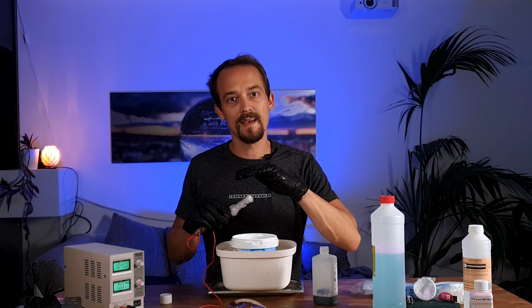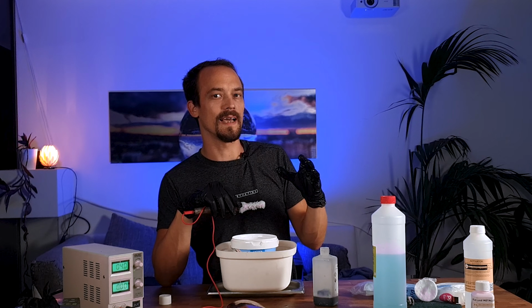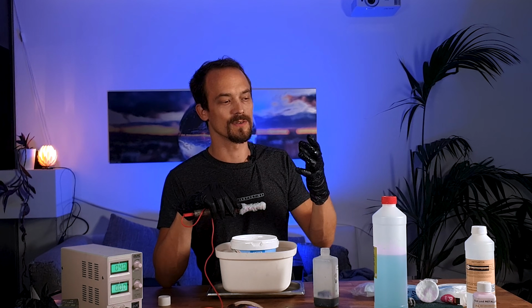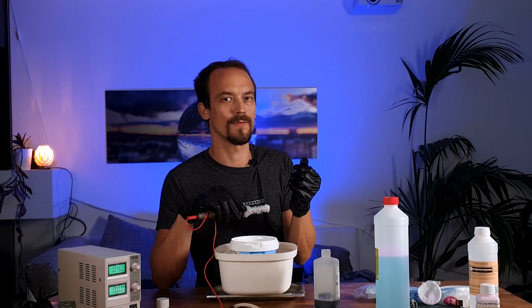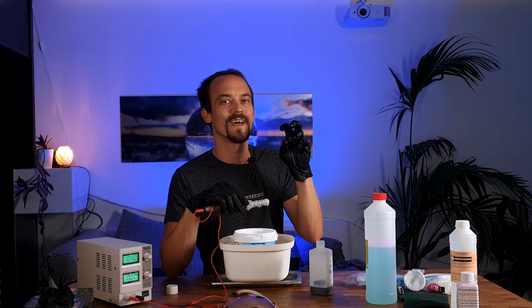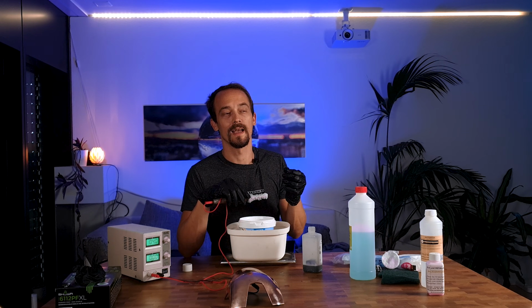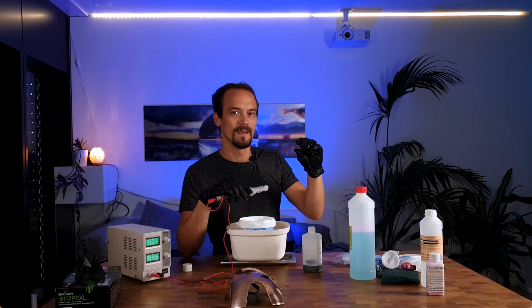The nickel is basically an in-between layer between the copper and the gold, because gold actually tends to mix with copper. That's what I did wrong the first time. So you want to have that nickel to separate the gold and the copper, because the copper is just the conductivity part of your part, your plating. The other purpose of the nickel is to give a hardened layer. So copper is really soft. Nickel is relatively hard.